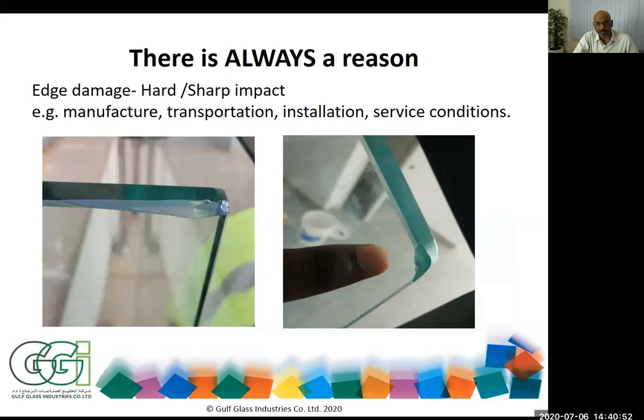And it is elegant, it is beautiful, because people tend to use glass as a beautiful material. And so there are no cover caps on it and no handrails on it, what we call exposed edge or frameless glass balustrades. But there is a concern, because when you are using these glasses, there's always a possibility that edges can get damaged. And rightfully, the UAE Life and Safety Code 2018 is one of the few codes that have made it mandatory, at least in the UAE, that balustrade glasses have to be laminated because it is a barrier.